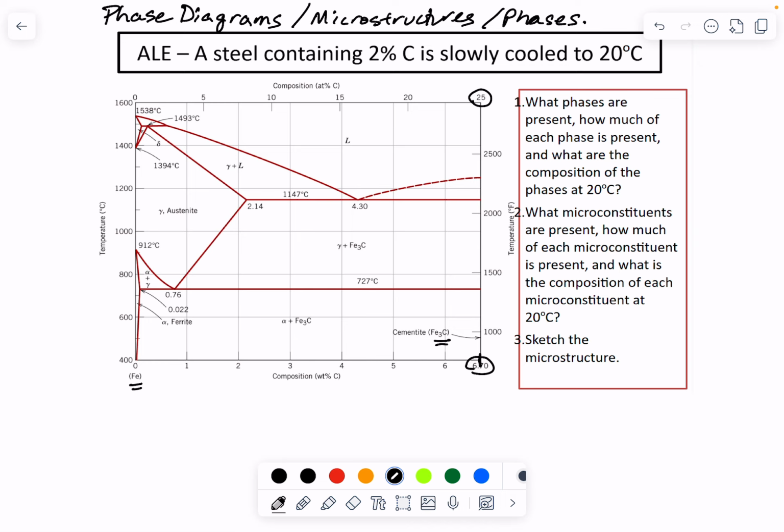So we're looking at the iron-Fe3C phase diagram, and I want to point out some reactions. This is review. Up here we see an invariant reaction at 1493. That particular reaction is called a peritectic reaction because we have two different phases, delta and liquid, turning into another solid phase, which is called gamma, which we call austenite. Gamma is austenite, and by the way, that's face-centered cubic.